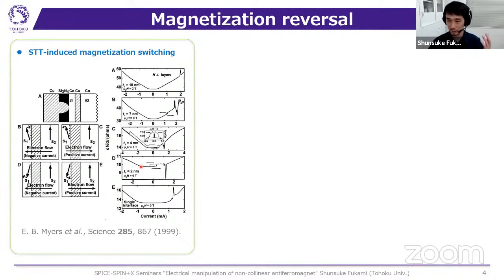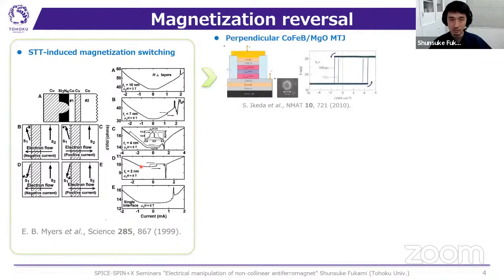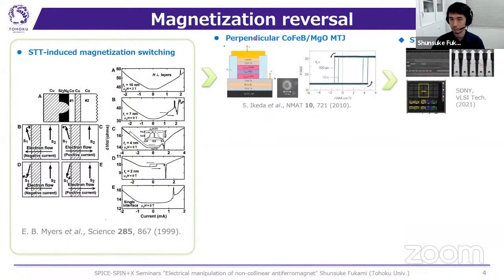And there are many important discoveries. One of the important discoveries is perpendicular easy axis CoFeB/MgO-based magnetic tunnel junctions. The importance of the discovery of this material system is that it can satisfy major requirements, such as a small switching current, a large TMR ratio, and good retention properties. And very recently, as you know, the spin transfer torque MRAM has been commercialized.